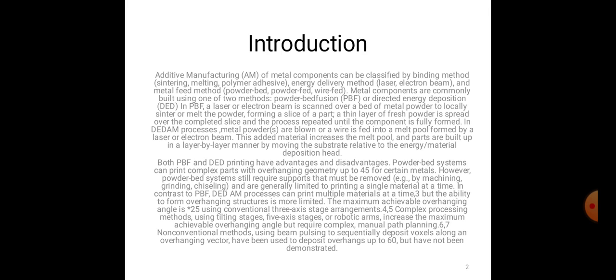Now let's explain additive manufacturing. Additive manufacturing of metal components can be classified by binding method, sintering method, melting, polymer adhesive, energy delivery method, laser, electron beam, and metal feed method. Metal components are commonly built using one of two methods, powder bed fusion or direct energy deposition. In PBF, a laser or electron beam is scanned over a bed of metal powder to locally sinter or melt the powder, forming a slice of a part.